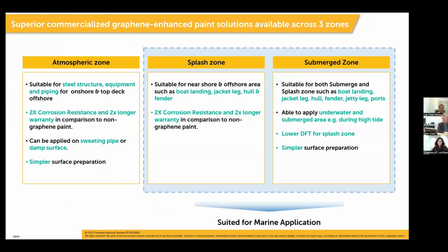So since we started ProShield Plus, of course, the focus at that time when we went into the market was primarily targeting the oil and gas segment, which, as you would know, has the most extreme corrosive environment. But even within these areas, we were looking very specifically at the atmospheric zone, and this would be our standard tolerance epoxy. Now, this is suitable for steel structures, equipment, and piping for onshore and top deck offshore. It carries 2x corrosion resistance, and it also comes with a 2x longer warranty in comparison to a non-graphene paint. You can even apply it on sweating pipe or damp surface.